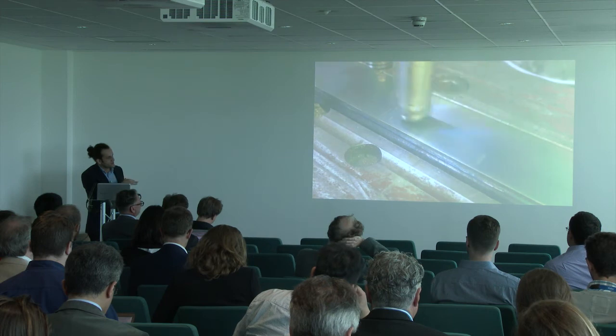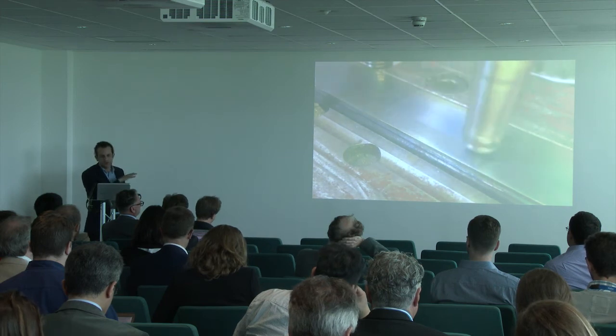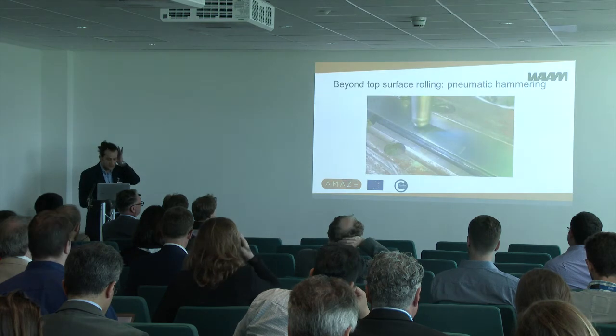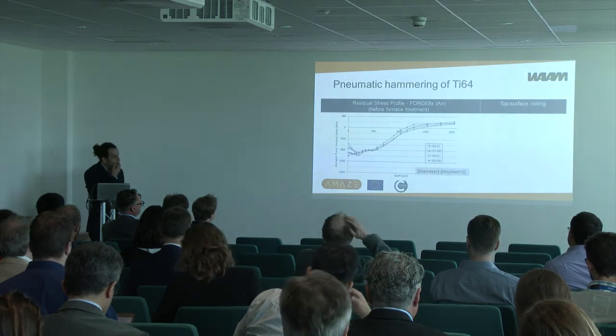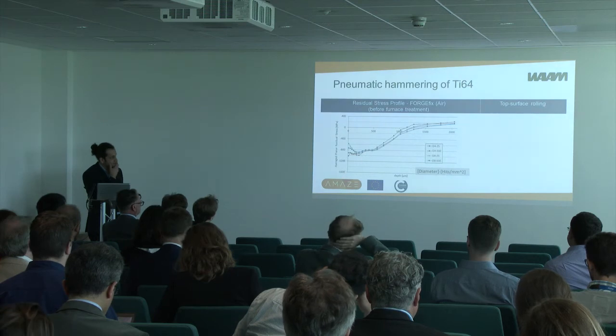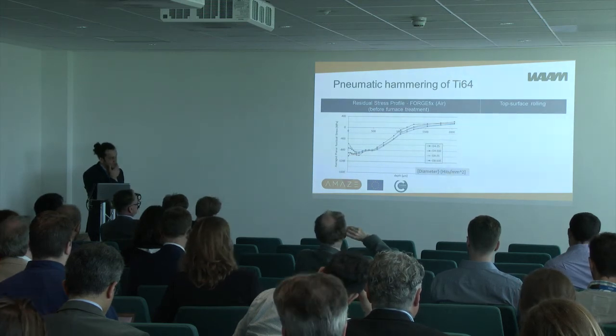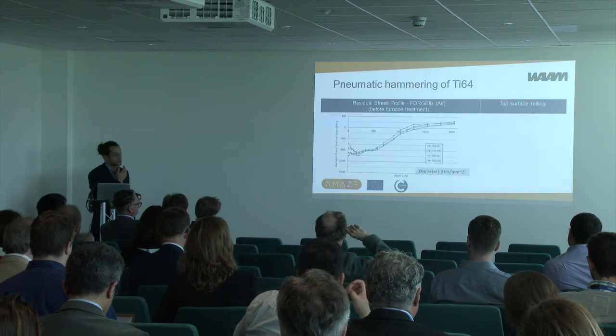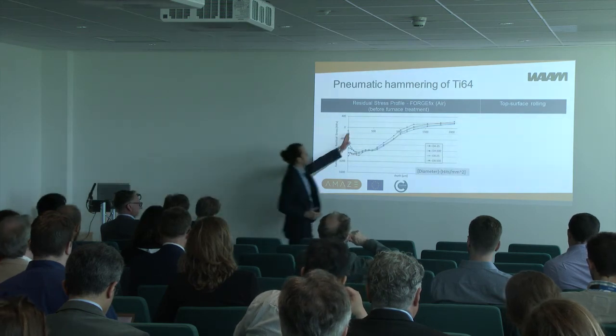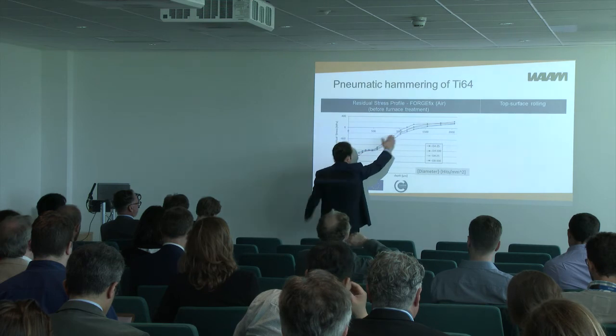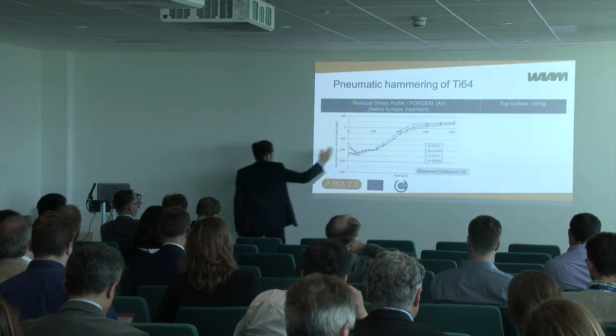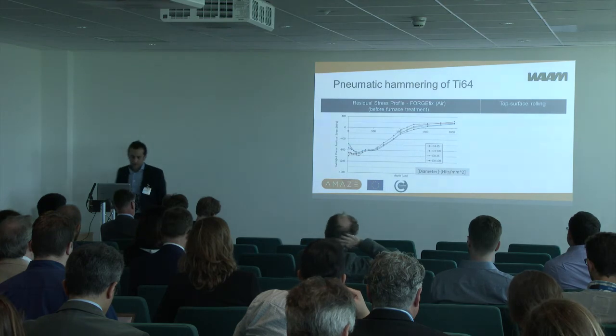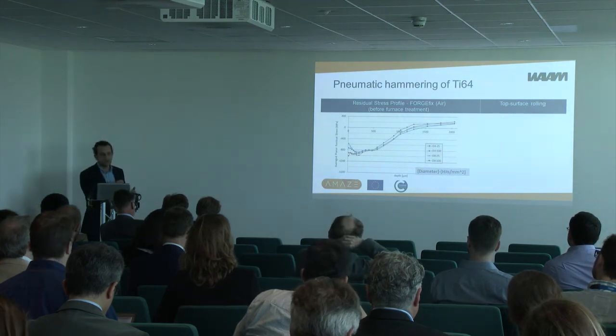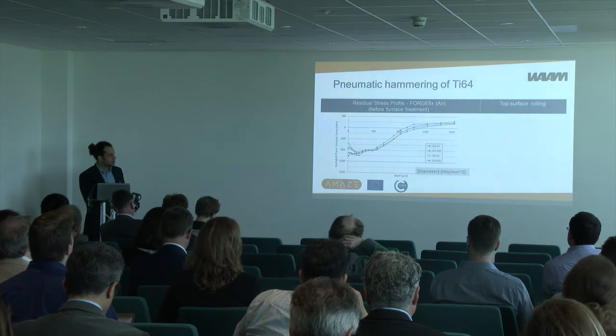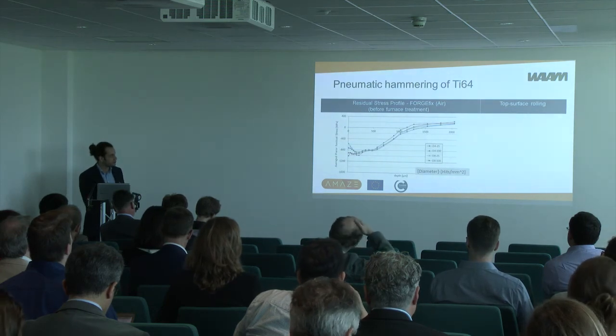In terms of characterization, to have as much clarity as possible, we applied it on machined surfaces, just because we wanted to be sure that what we were seeing was the real effect of the tool. And the good news is that if you look at the residual stress plot that we've got here, it is very effective in introducing superficial stress. In fact, this is the surface. This is 1 millimeter below the surface, and you can see there is a lot of compressive stress, up to 1,000 megapascal in the case of titanium. In fact, the yielding compression is higher than the yielding tension, and so we can introduce a lot of cold work in this material using that tool.